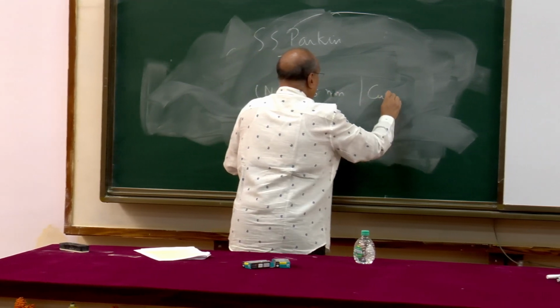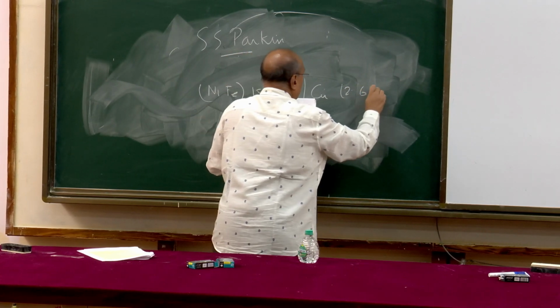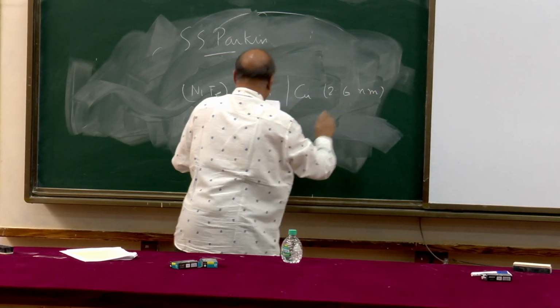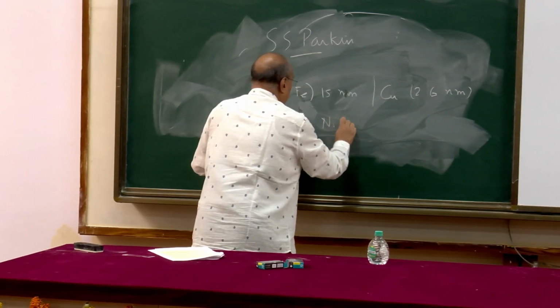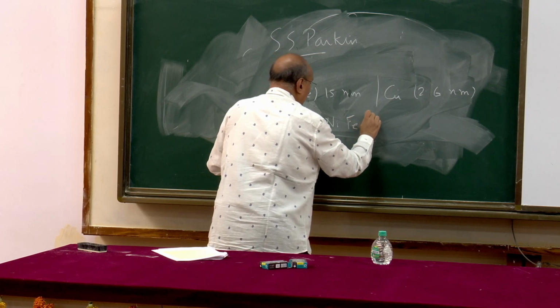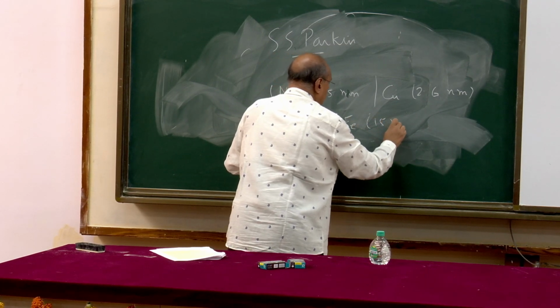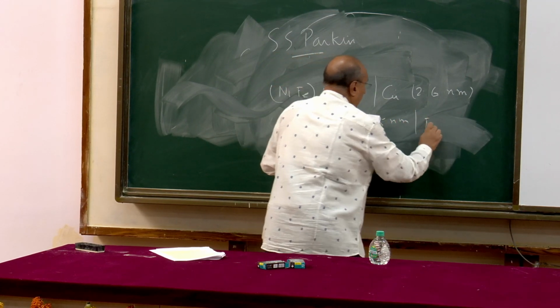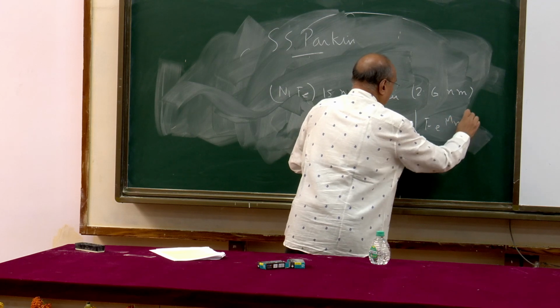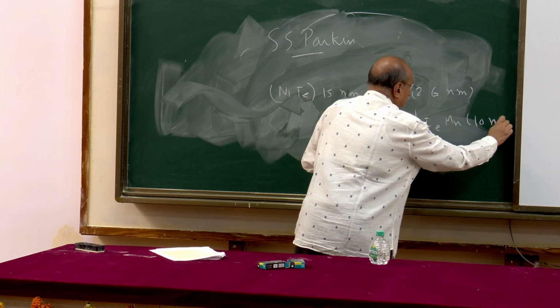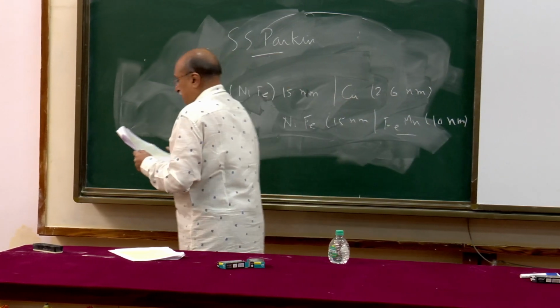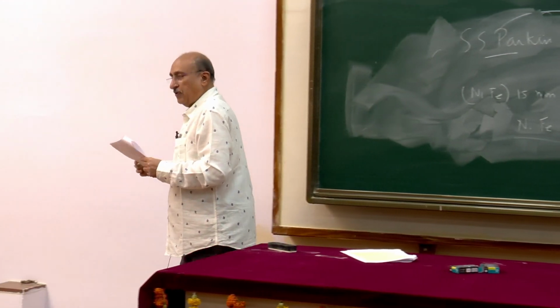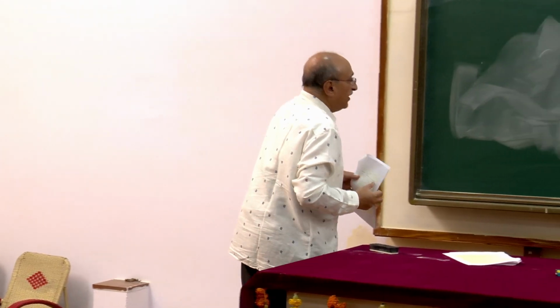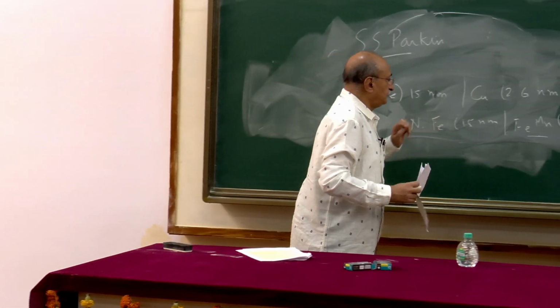Then copper, 2.6 nanometer. Again, nickel iron permalloy, 15 nanometer. And iron manganese, which is 10 nanometer. Four layers. The two magnetic layers that I am talking about are these two.